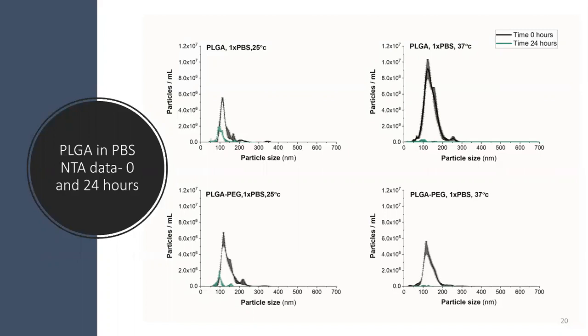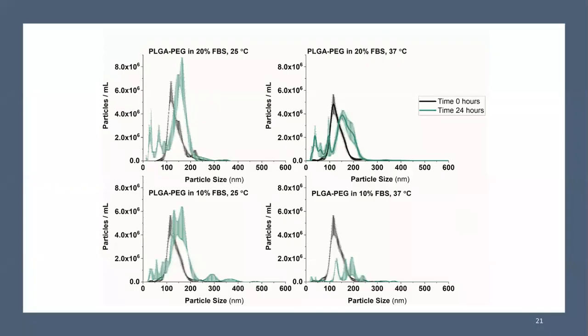And overall particle concentration decreases irrespective of surface coating or incubation time and temperature. And this effect is most pronounced at physiological conditions, which isn't particularly surprising. And we see much the same thing when we incubate the PLGA and PLGA-PEG nanoparticles in fetal bovine serum. So why does the particle concentration actually nosedive like this?